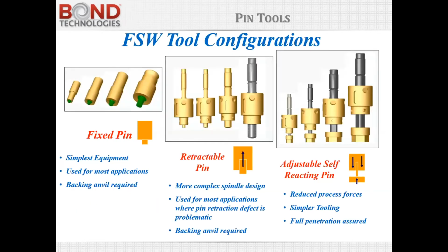Not only are some tools fixed pin, but there are some variations on the pin tool design. The fixed pin is shown to the left. These can actually come in a one-piece or a two-piece configuration. We make tools that have the pin as a separate component with a backing screw so that you can change the pin length depending on the material thickness. The pins shown in the middle have two pieces, but the pin axis and the shoulder axis are actually separate.